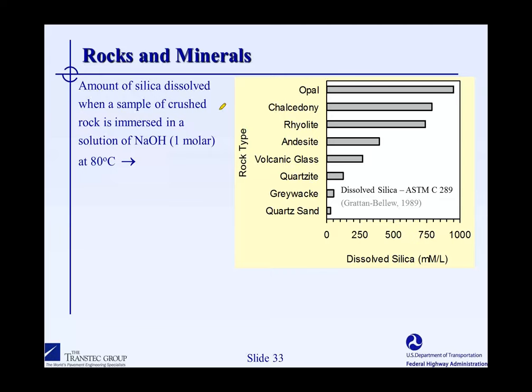Just to give you an example of the different reactivities of different types of mineral and aggregates, we have a graph here that shows a list of different rock types. What we're seeing on the x-axis is the amount of dissolved silica, the amount of silica that dissolves when that aggregate is placed in a solution of very strong alkali at a high temperature. 80 degrees Celsius is 176 degrees Fahrenheit.